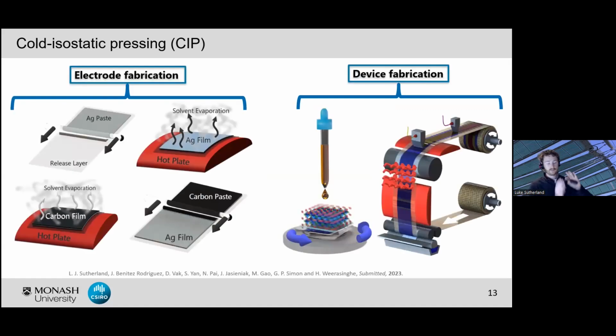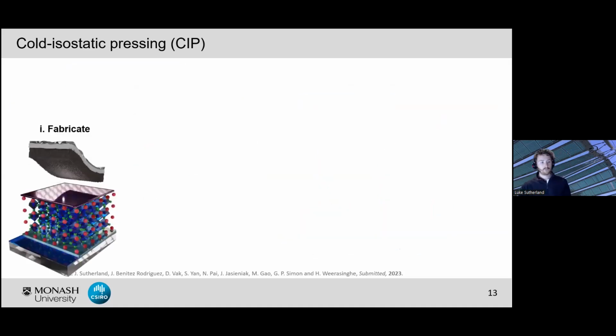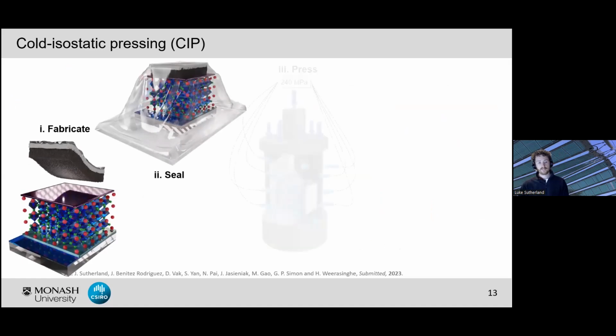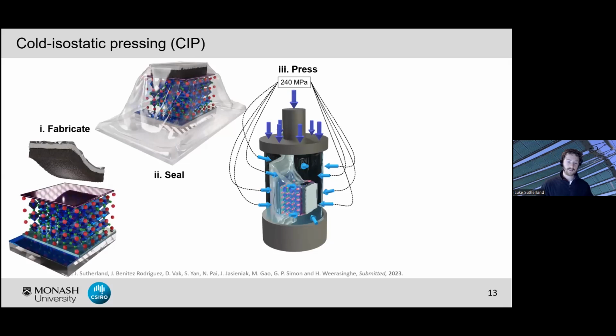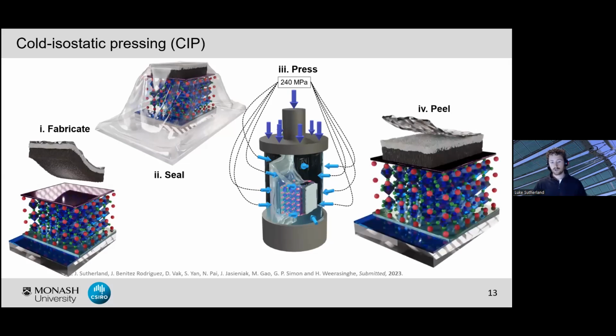Now we start off, complete electrode fabrication is exactly the same as what we did before, coating our two pastes onto our non-stick release layer. And in this work, we fabricated devices both on rigid glass, by our traditional means of spin coating, and also looking at our roll-to-roll fabricated cells as well. And a relatively simple process. So we fabricate these devices. We then seal them in a vacuum sealed bag before completely submerging the device in our CIP chamber, which is filled with water. We then apply our pressure of say 240 megapascals in this case, and then that transfers the electrode to our underlying spiro hole transport layer. Then we can just pull the device out and peel off our release layer at the end, again exposing our electrode film for electrical connection.